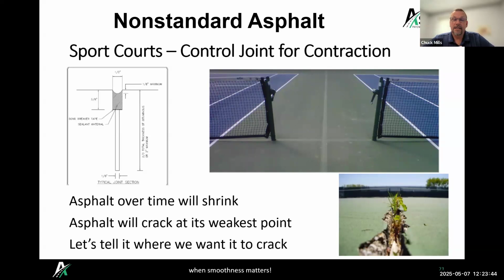So one good way to control that is putting in control joints, sawing and sealing control joints into that surface. And then that can control where those cracks are happening. So, for example, like this picture here with the tennis court, they put a control joint right at the fence post line where the net is, and then in between the courts. And that's a pretty good practice because there's a lot of stresses and strains even from the nets. Those posts have a lot of tension on them, so that can cause more tension and you can get cracking around there. But if we can control those cracks in between the courts, then it's not on the playing surface. So it's a good control measure to control where those cracks are.